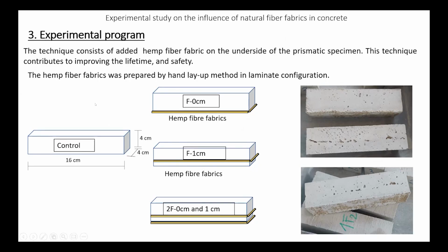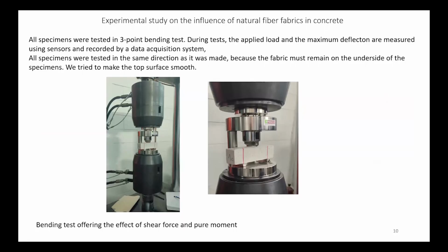The hemp fiber fabrics were prepared by the hand lay-up method in a laminate configuration, and afterwards all specimens were tested in a 3-point bending test. During the test, the applied load and the maximum deflection are measured using sensors and recorded by a data acquisition system. All specimens were tested in the same direction as they were made, because the fabric must remain on the underside of the specimen. And we tried to make the surface smooth for a better test. In the bending test, the effect of shear force and pure moment is observed.